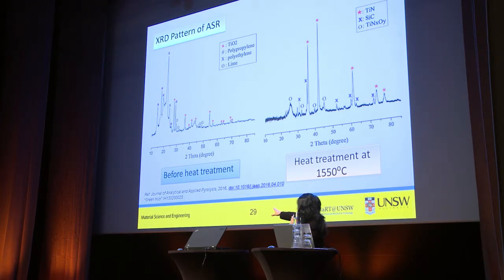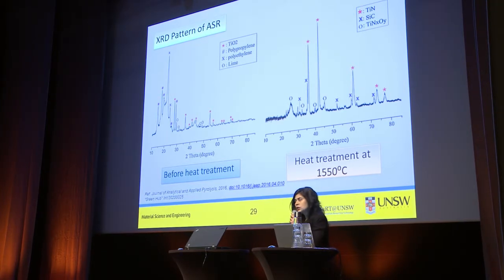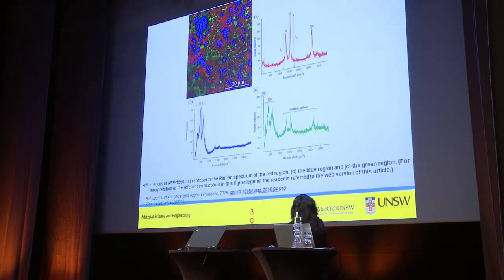You can see that before heat treatment, polymers all intact. You've got TiO2, as I mentioned earlier, in this particular mix. You can see after heat treatment at 1550 that we've transformed these into titanium nitride, silicon carbide, and of course, all of these are highly expensive, high-performing materials. Again, a lot of work on Raman imaging that we've done here, and you can see not only that you've identified TiN, for instance, and SiC, you've also shown that the carbon that's being produced is highly ordered in nature. So lots and lots of new opportunities to explore.